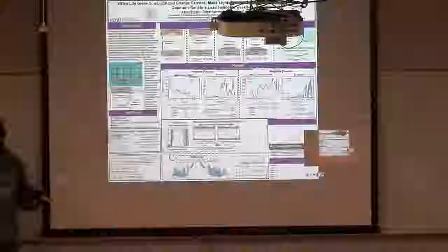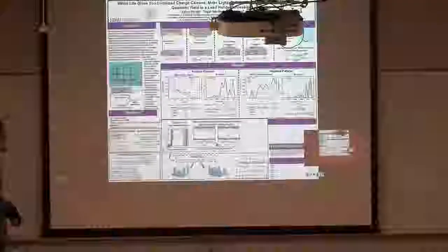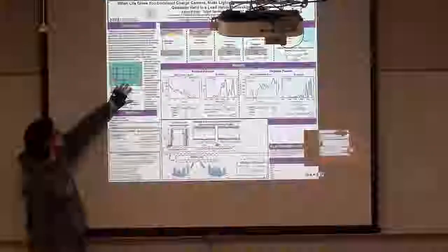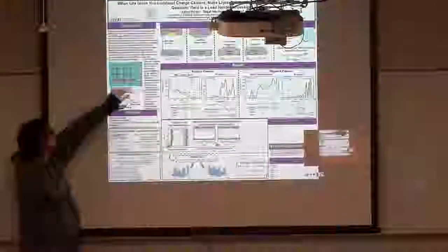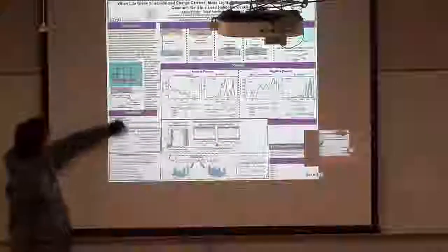But we're going to try to take these polarons and make them emissive in the IR region, because some experiments have shown that polaron absorption happens in the IR region, where people would be interested in getting an efficient IR emission. And just to illustrate polaron formation in these materials, this is a 2D projection of our perovskite cluster, our nanoparticle, surrounded by passivation ligands.